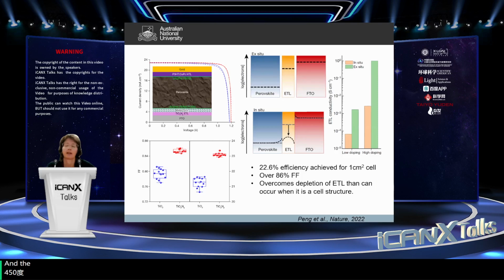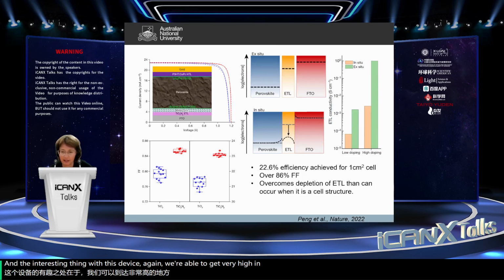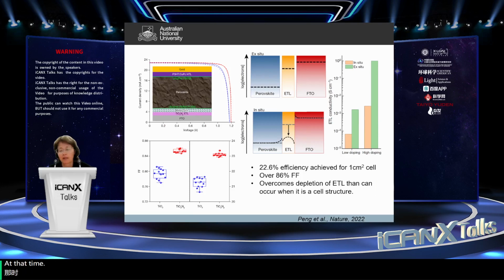Now, the interesting thing with this device, again, we were able to get very high fill factor. So this was over 86% fill factor, 22.6% efficiency for a 1 square centimeter cell, which was the highest at that time. And what you find here is quite counterintuitive, is that the conductivity of the electron transport layer is actually different when it's inside the device and when it's outside the device. This is something that was initially very surprising.